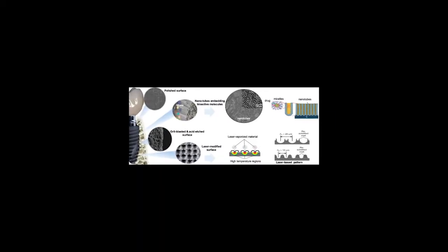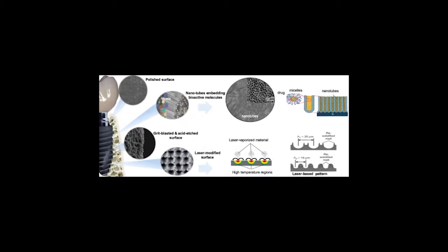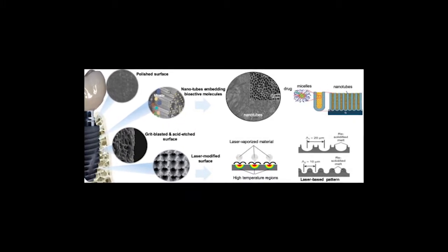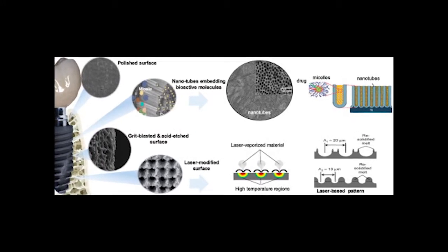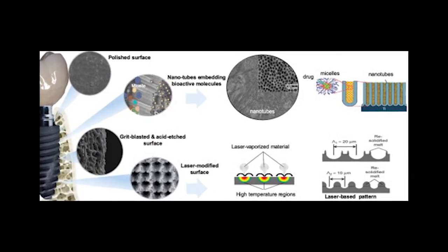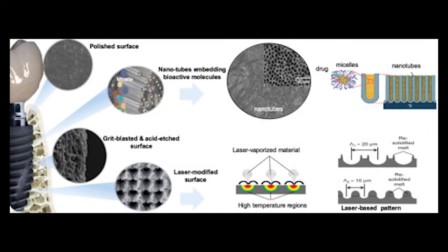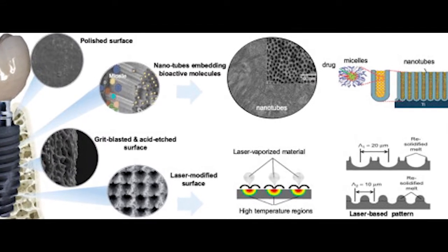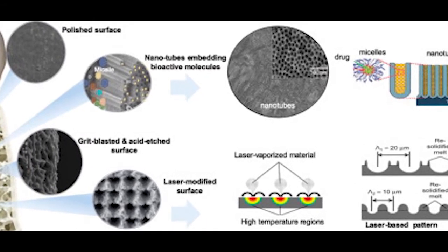The modification of implant surface structure is carried out at the nanoscale. The key is to decrease bacterial adherence and mechanically lyse microbial cells on the surface of contact. The nanopatterning is created by modifying surface finishing techniques. For instance, creation of nanopores, nanotubes, nanowires, and hydrothermal treatment has demonstrated efficacy in preventing biofilm formation.